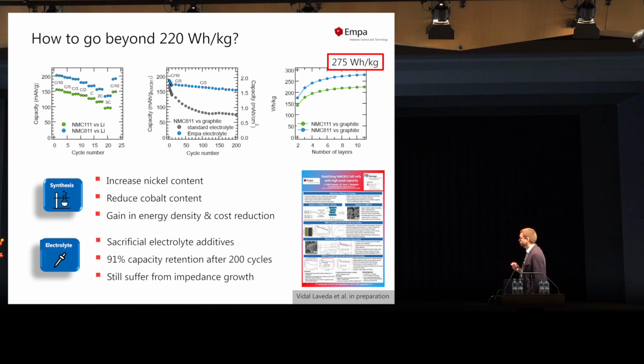The problem now with nickel-rich cathode materials is that their stability is much worse than in the NMC 111 case. They have much higher surface reactivity and lower intrinsic stability. And you can see here, if you just put these materials now in a standard cell, which works well with NMC 111, we have a very rapid fading.